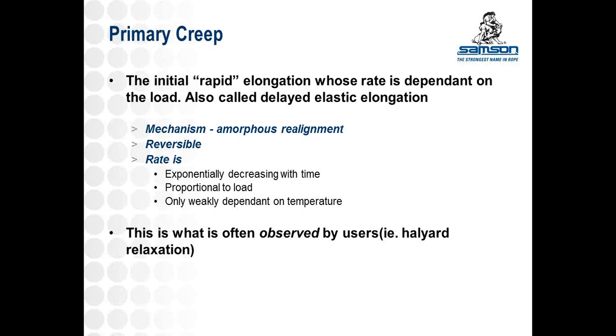So to break it down in a little bit more detail, this primary creep, this is that rapid elongation. And what you really have taking place here is not so much the polymer chains sliding past each other yet, but rather there's a slight reorientation of what we call the amorphous zones. So most of the fiber, most of the material that makes up the rope is what we call crystalline or pseudo-crystalline. The molecules have very specific locations next to each other. They're basically all standing in line. You do, however, have small regions where a tangle still exists, where they're not all standing in line nicely. They're still kind of mixed up like the spaghetti in the bottom of the bowl.